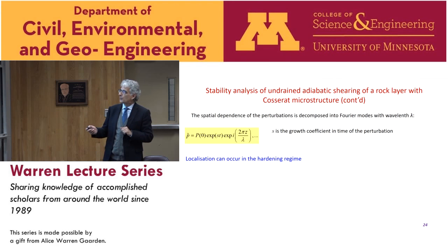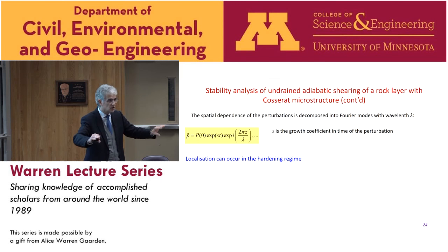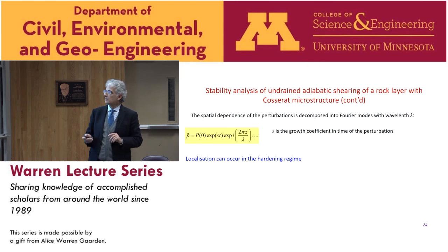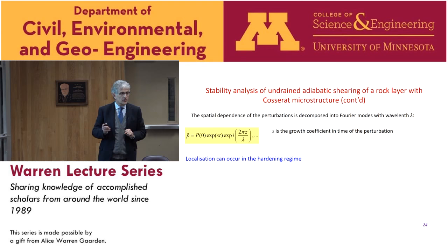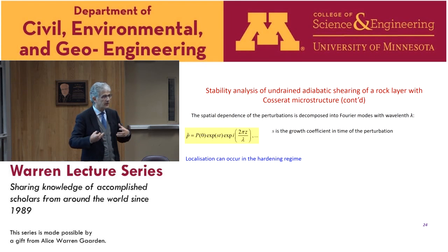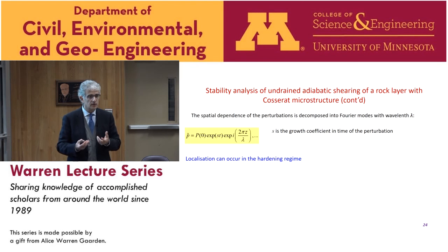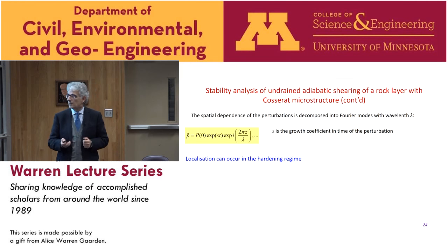Okay, so when we perform the perturbation, we decompose the perturbation into Fourier modes. Lambda is the wavelength of the perturbation, and the solution in time is exponential. So we solve the problem in terms of s, which is the growth coefficient of the perturbation. If s is negative, it means that the perturbation vanishes. If we find solutions for which s is positive, we have instability. The first interesting result is that, because we have the effect of thermal pressurization of the fluid, if the dilatancy is not strong enough to compensate the thermal pressurization of the fluid, we can get instability even in the hardening regime. So the effect of the thermal pressurization is to have earlier instability.